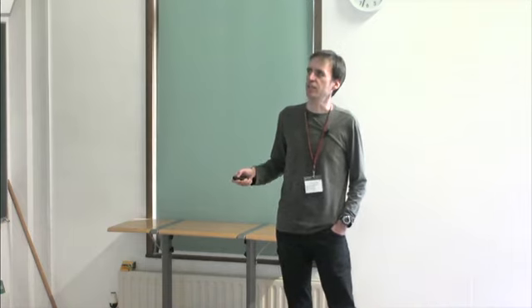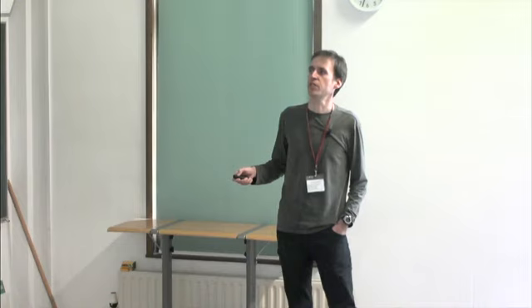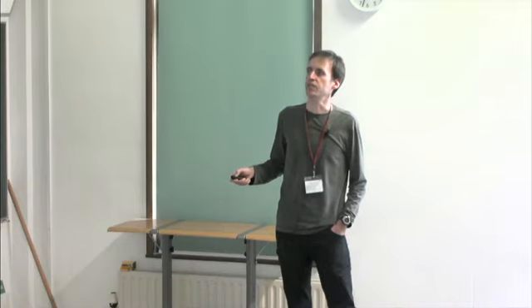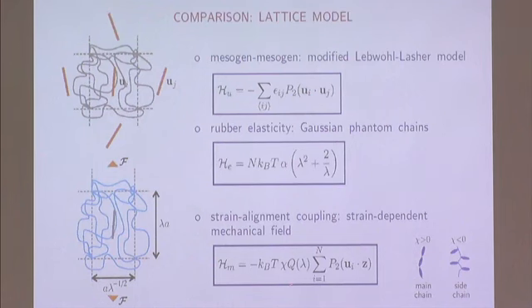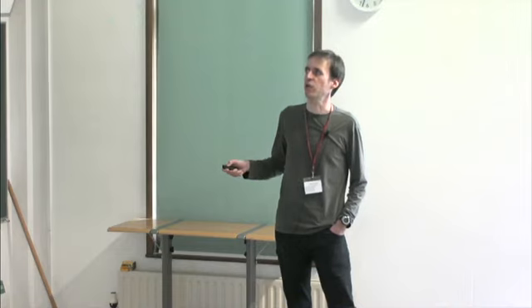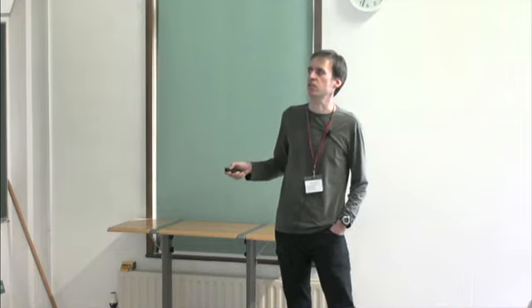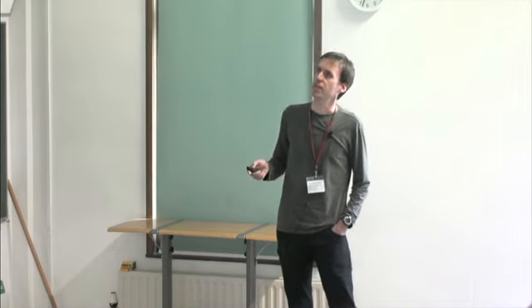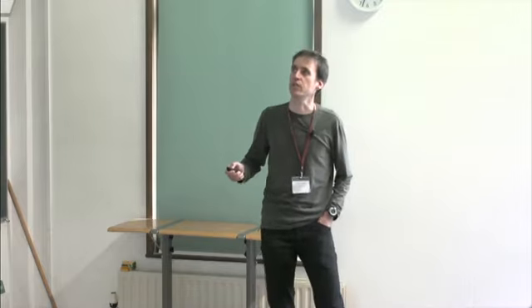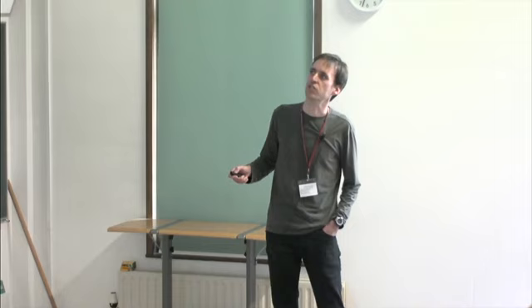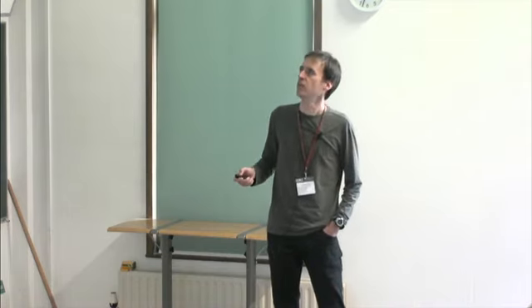Then we have another parameter here, chi, which will help in determining the magnitude of this internal mechanical field. It turns out that if you take chi positive, this will result in an alignment along the pulling direction, like in main chain systems. If we go with a negative chi, this corresponds to the opposite situation, like in a side chain system. And again, we perform these stress-strain experiments, pulling, and here you have the stress-strain isotherms, and they're pretty similar to what was seen for the Gay-Berne system.